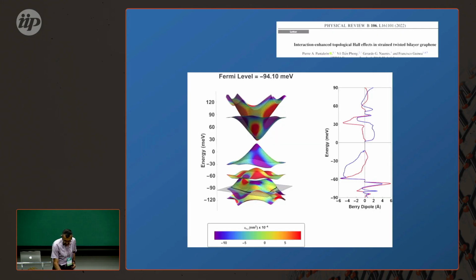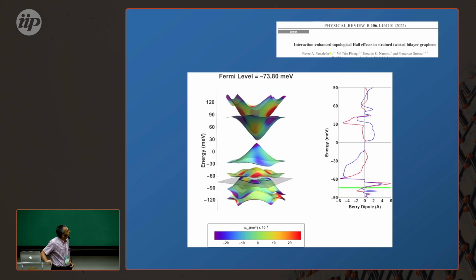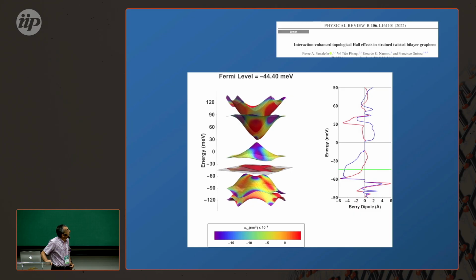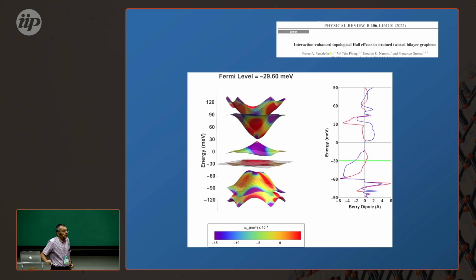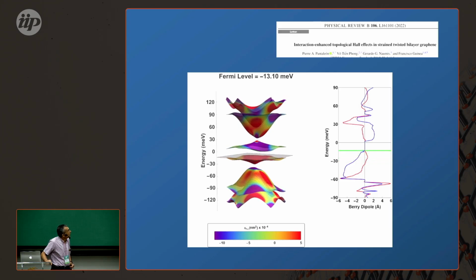As I said, as a result, as you increase the filling, the bands are changing. Now you see the chemical potential is rising. Now it hits the central bands, and you see that they're changing very, very much. You only have really flat bands at neutrality, when the valence band is filled and the conduction band is empty, and eventually you will distort the other band.